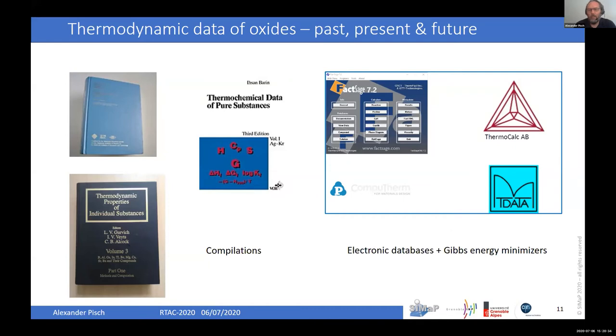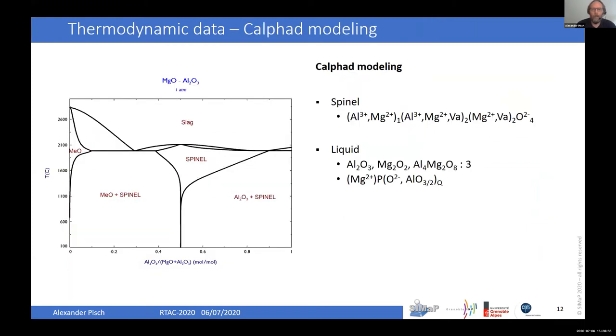For about 30 years now, we tend to put these data into thermodynamic databases electronically. The advantage is that you can then use the data directly with Gibbs energy minimizers, and with the Gibbs energy minimizers, you can do thermodynamic calculations. In the compilations, you basically have stoichiometric phases, but you can also use the data to do CALPHAD type modeling.